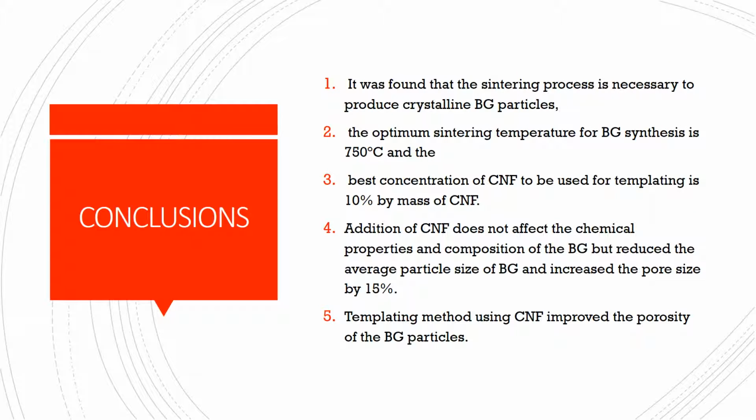Next, for the conclusions, it was found that the sintering process is necessary for the production of crystalline bioactive glass. The optimal sintering temperature for bioactive glass synthesis is 750 degrees Celsius, and the best concentration of CNF to be used for templating is 10% by mass of CNF.